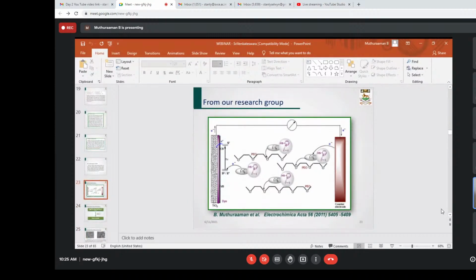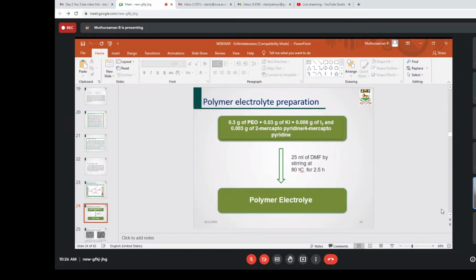From our research group, we also contributed to that, which is an ion complexing agent with the redox couple. So you can see a stick-like structure. That is the polymer which you can see here. So we got a 4.1% efficiency. So this is how we make the polymer electrolyte.